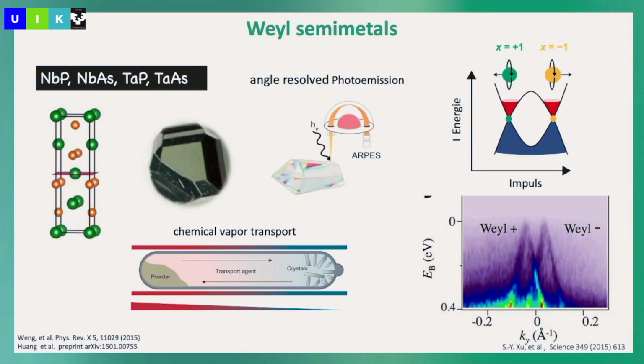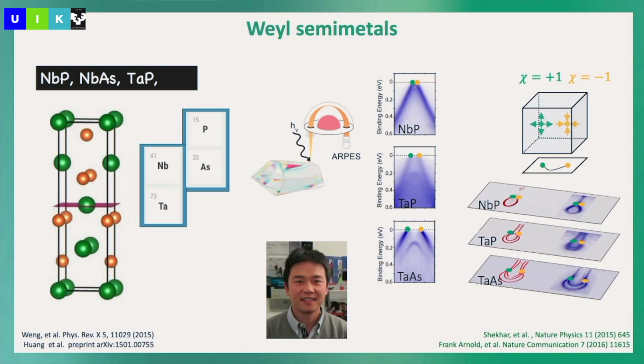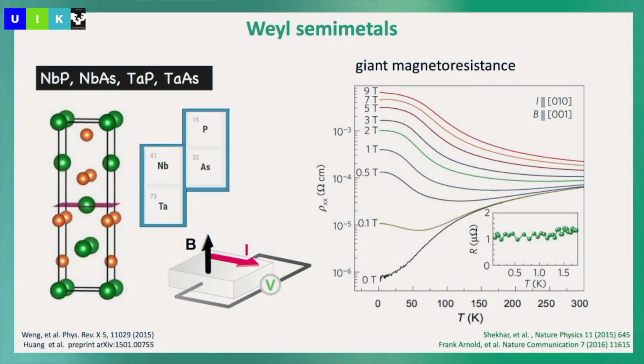And here we also made this material. Here has nice big crystals, and you can see nicely that they have really the electronic structure here in photoemission. The sign here for the Weyls are made artificially. This is not measured. Anyway, so you see this nice linear dispersion in these materials, and so we made all the crystals, and you see if you make the binary materials more heavy, the band splitting becomes larger, and here the surface state is the calculation and the measured surface state. It's really amazing how nicely it agrees in this simple material with a single particle picture.